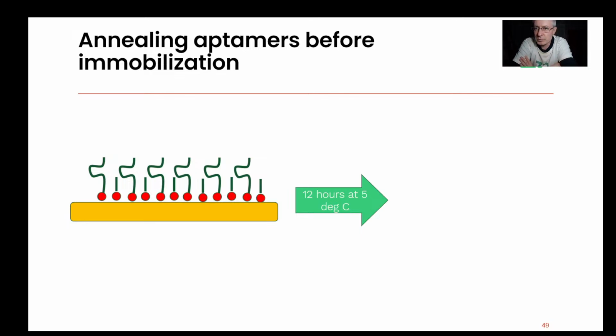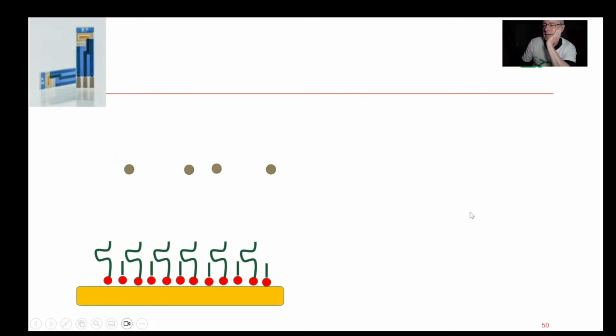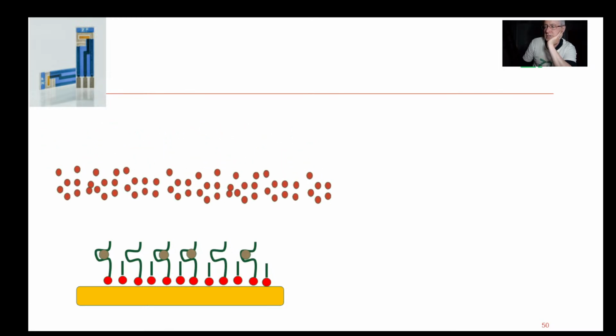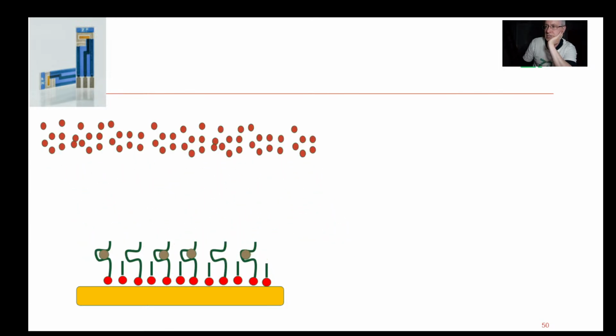What we would do is we would form this thiol bond. We would form this self-assembled monolayer with the aptamer, have some MCH in there as well as a separating molecule, and we would leave that sitting in the cold for about 12 hours to essentially let the surface arrange itself into its lowest energy state. We don't necessarily add heat in order to help it anneal. We don't, is the quick answer. And then you should be ready to read it. And by reading it, I just mean bind to your target, which I think was thrombin, if I remember rightly.